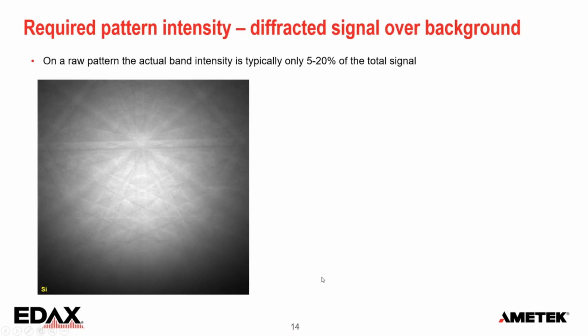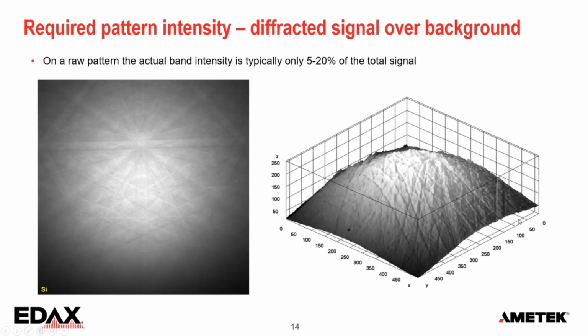So if we go to the unprocessed pattern, then if we stretch the image a little bit more, this is what it looks like. So we get an intensity gradient with the highest intensity more or less in the middle, and the bands are just superimposed on this gradient. And it's difficult to really quantify. It's also difficult to actually measure it. But when you estimate the height of some of these bands, of course, it's also even orientation specific. The actual band intensity is about 5 to 20% of the total signal.